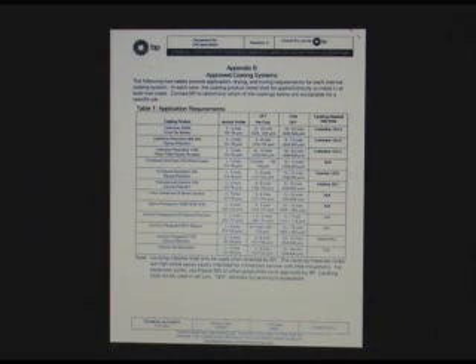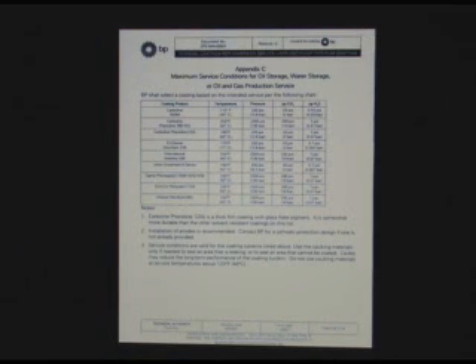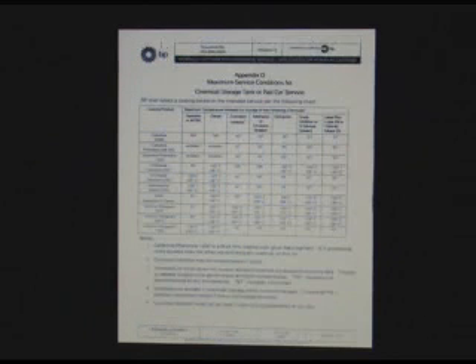In the left-hand column, he gives us the trade names and the generic names of the coating of the lining system, the anchor profile, the dry film thickness, and the total film thickness. Click again, please. And also, in this case, how to apply it by temperature, pressure limitations, and then partial pressure of CO2 and partial pressure of H2S limitation. Here gives another guide for which surfaces these linings are applicable.